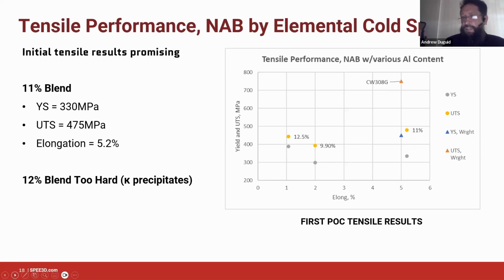Now, our guess, not that we've done the science on this, but if I had to guess, I'd say that the 11% is working a bit better because it's actually sintering a bit better. And that's pushed the data point out, if you look at it, in a northeasterly direction. So it's both got more elongation and higher strength. And really the only way that you can do that is by either reducing the defect size or improving the fracture toughness. So that's probably a sintering thing. That's why we say that. Would I bet a sheep station on it? Maybe not, but that's probably what's going on.